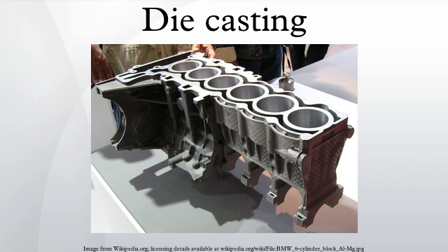Maximum weight limits for aluminium, brass, magnesium, and zinc castings are approximately 70 pounds, 10 lb, 44 lb, and 75 lb, respectively. The material used defines the minimum section thickness and minimum draft required for a casting as outlined in the table below. The thickest section should be less than 13 mm, but can be greater.